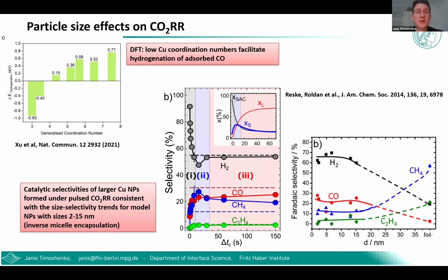which they supported also by DFT simulations. On the other hand, in the regime we enter when we apply longer potential pulses, where we form bigger particles, the observed selectivity trends match very nicely with the general observation about the size dependency of CO2 electroreduction product distribution on particle sizes, which were again obtained in our earlier studies using bigger particles produced using completely different synthesis approaches. So it really seems that these pulse reaction protocols allow us to bridge between these different studies of ultra small systems and studies of larger particles.